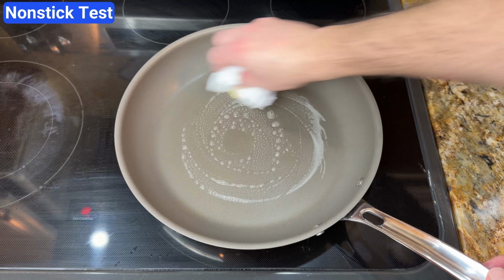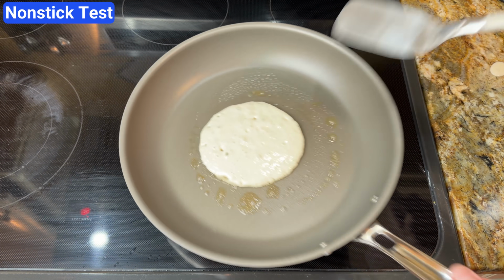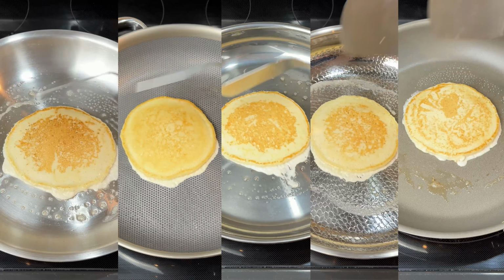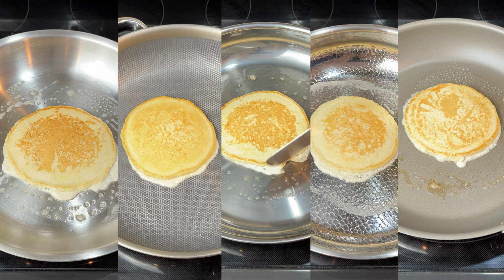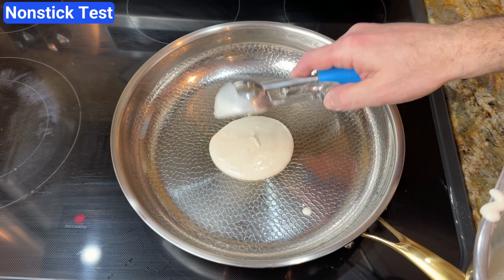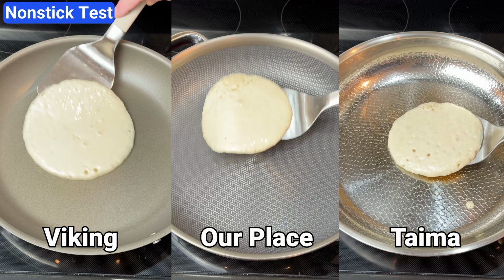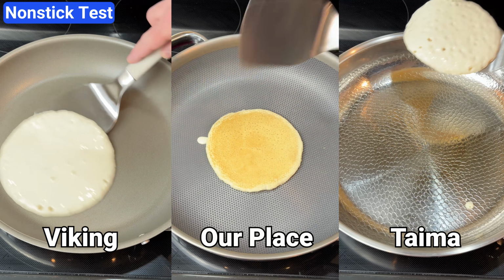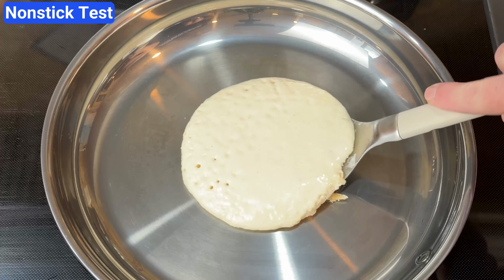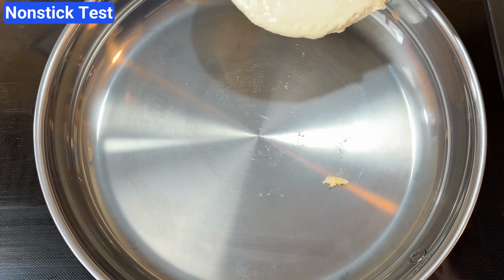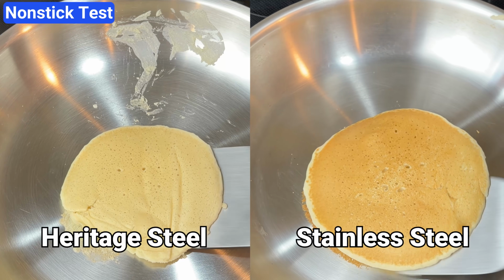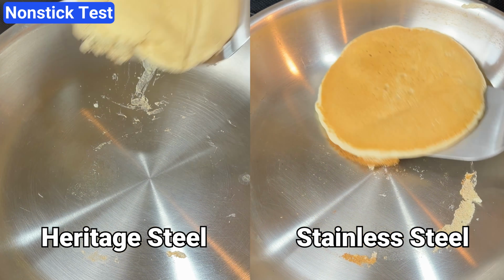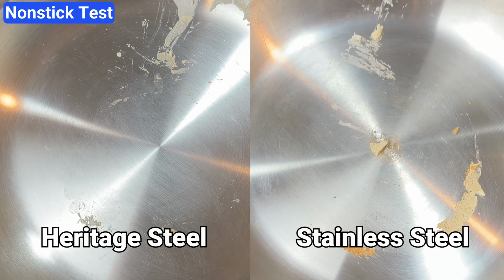After the eggs, I spread a thin layer of butter on each pan and cooked pancakes. Every pan passed this test without sticking. I did another round of pancakes, but the second time I didn't use any butter. Viking, Our Place, and Taima all performed great. The pancakes stuck a little bit to the Hestan pan, but not much. The Heritage steel and stainless steel pans stuck the most, but the pancakes still came out fine.